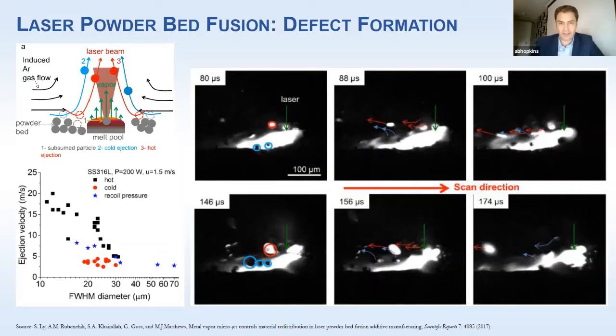A good analogy is taking a water blast or a water cutter and spraying it on sand. You're just blasting particles out of the way. Then you begin drilling into the substrate, as shown on the previous page, and particles fall into the melt zone, into the hot zone, and that's how you get most of your material: particles adjacent to the melt pool falling in. Naturally, when you get all this vapor, you have a blast. It blasts the particles first out of the way, so they fly out, but then you have a compression wave, a shock wave, and the gas pushes the particles back into the melt pool.